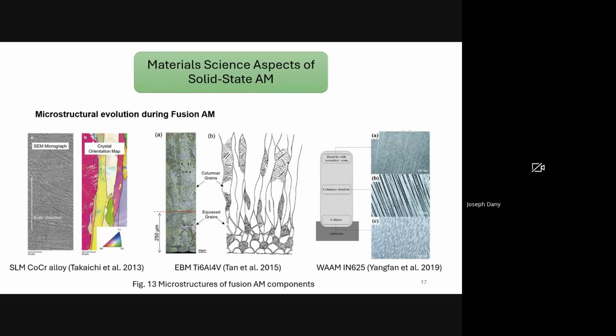For example, in nickel-based superalloys like Inconel 625, SLM produces fine columnar or epitaxial grain growth aligned to the build direction with a strong crystallographic texture. The rapid solidification also produces a supersaturated solid solution and fine precipitates, enhancing strength, but sometimes resulting in residual stresses and anisotropic mechanical behavior. Scan patterns and laser parameters influence grain orientation and size, with different scan strategies yielding varied microstructural features and mechanical anisotropy.